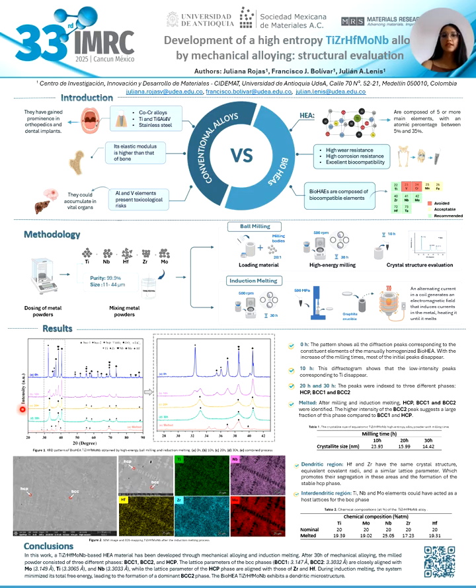After 20 and 30 hours of mechanical alloying, the peaks were indexed to three different phases: a hexagonal compact structure and two body-centered cubic structures, BCC1 and BCC2. The most intense peak is observed at 40.5 degrees with a preferential orientation in the 110 plane and is associated with the BCC1 phase rich in molybdenum. On the other hand, at 38.6 degrees, a BCC2 phase with an abundance of niobium is evident.